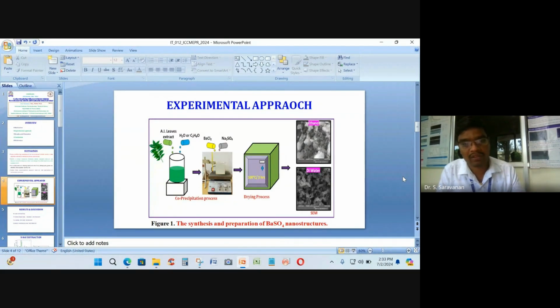It was boiled at 80 degrees Celsius for 1 hour. Then we got that extract, then added it into the water. Then barium chloride and sodium sulfate, both are precursors to get barium sulfate. So finally, I got a white precipitate. So again, I kept it in the drying process at 100 degrees Celsius for 2 hours.